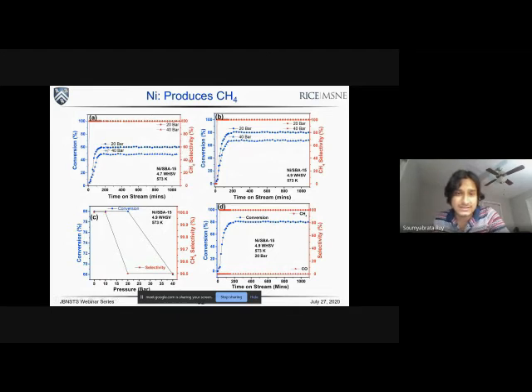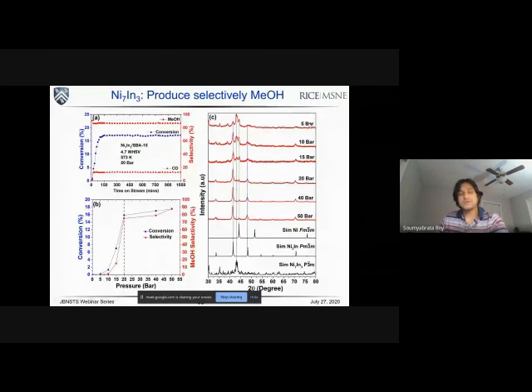So the interesting story here is that when we use just pure nickel, we get 100% selectivity towards methane. You can see this from this graph. On the right hand side, the blue-red axis, you can see the methane selectivity, and at various pressures and temperatures we can see that when we use pure nickel, we always get methane. But we wanted to form methanol. So interestingly, when we form these ordered structures of nickel 7 indium 3, the methane conversion drastically changes to methanol conversion. And you can see from this graph that there is a certain conversion and selectivity, and the material that we synthesized is almost 90% selective for methanol. Another interesting phenomenon that we observed is that during this transformation, the material itself also changes to a certain crystallographic phase, which is the active motif for doing this kind of catalysis.